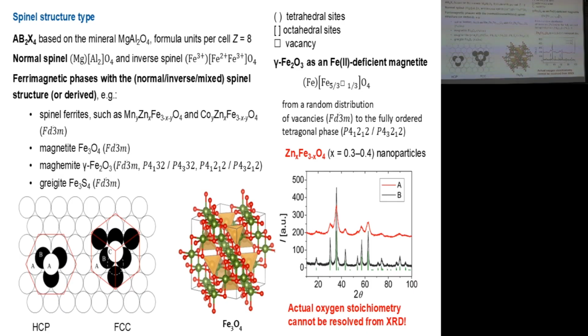It has actually the same crystal structure, but there is less iron on octahedral sites. So you can formally describe it as some spinel with vacancies on octahedral sites. And from the viewpoint of structure, these vacancies might be completely randomly positioned, or they might be positioned in some regular pattern with certain symmetry, specifically with tetragonal symmetry. And of course, there can be a varying degree of ordering. So you can prepare a maghemite with completely randomly distributed vacancies on octahedral sites, or fully ordered maghemite with vacancies in some clear pattern.